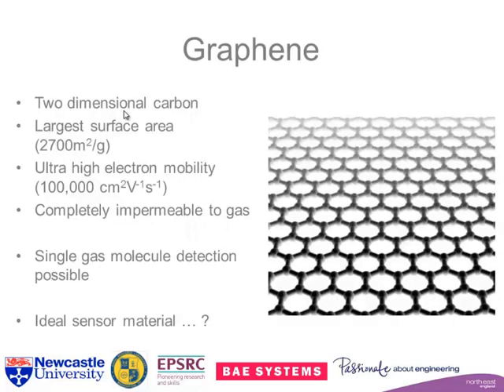So graphene then is two-dimensional carbon. It's the building block of nanotubes and graphite. It's got the largest surface area at 2,700 square meters per gram. It has potentially got an ultra-high electron mobility. However, this is for graphene that is perfect and freestanding. As soon as you put it onto another material, this mobility drops. Epitaxial graphene is typically around the 5-10,000 mark. It's completely impermeable to all gas.